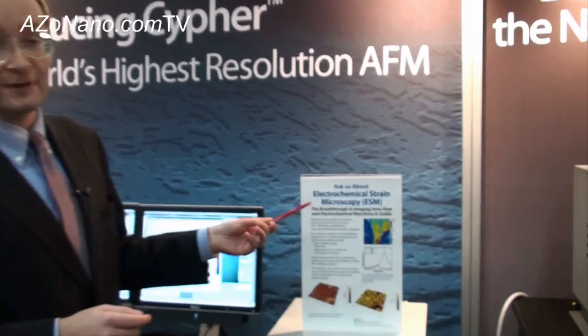A simple example is that if we have a conventional material such as lithium cobaltate, if we extract just 10% of lithium atoms from just one unit cell, it generates the strain that can already be measured by an AFM. So this is the gist of it. By measuring electrochemical strains, we can detect electrochemical reactions at volumes which are a billion times smaller than conventional methods. Everything else is engineering. Engineering took us 5 years, and it heavily involved a lot of collaboration with folks at Asylum, for whom it took much more. But this is the crux of this development.